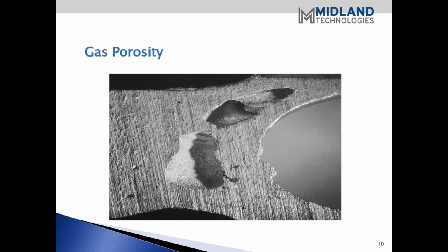This is another example of gas porosity, and you see this is one of the challenges, I think, for most casters until you become accustomed to viewing the two different styles of porosity, shrink porosity and gas. This is a real good example of gas porosity. You'll note that the surface of the pore is usually fairly smooth. Not always, but generally speaking. And you can also get an idea from the location of the porosity within the casting. It's a good example of gas porosity trap. Next slide.